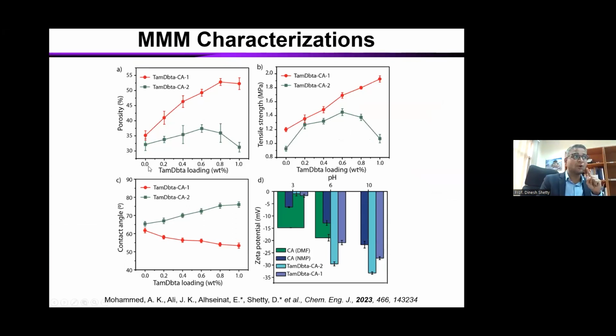When you have 0, it means it's a pure, pristine cellulose acetate membrane. And when you go up to 0.8, the porosity is drastically increased in a well-dispersed system. CA1 means well-dispersed, CA2 means a relatively less dispersed system. And if you think about the tensile strength, that's important for the membrane application.